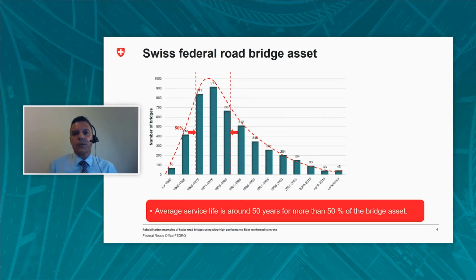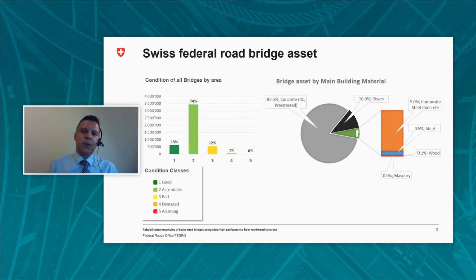Degradation process, increase of traffic load, especially heavy traffic load, as well as evolution of codes make it necessary to proceed regularly to important rehabilitation projects for several of these bridges. With an annual investment of around 1% of the replacement value, the bridges are kept in a good or acceptable condition. Concrete is the predominant building material in Switzerland for our road bridges. 83.5% of the total area of the bridge decks is associated to reinforced concrete or prestressed concrete bridges.